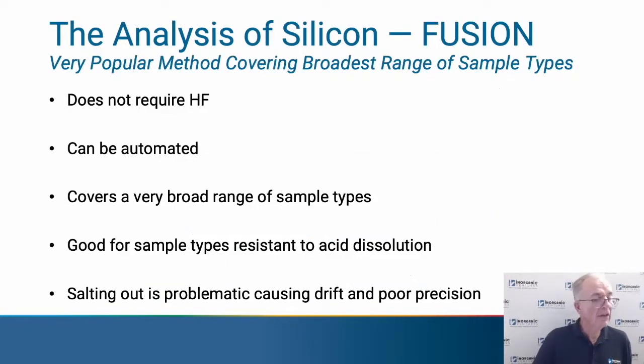The fusion method does not require hydrofluoric acid. It can be automated. It does cover a very broad range of sample types. It's good for samples like, let's say, silicon carbide that are resistant or impossible to do really by an acid attack.